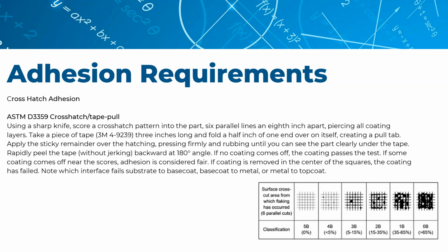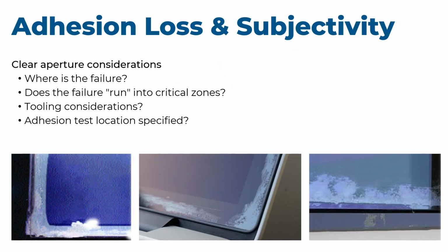And as you can see here on the slide, we basically have a whole spectrum of failure. Depending on what your customer specifies, you could see through this failure mode what is acceptable. Can I take up to a 3B, 5 to 15% loss? Is that okay? You can also say, after 1 pull, I want 0% loss. After 20 pulls, I want 3B. After 100 pulls, I would expect 1B. So again, this is kind of collaborating with your coating supplier and understanding what the film is capable of.